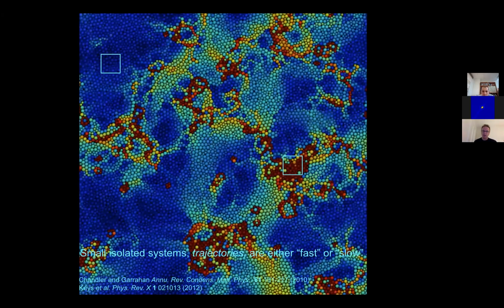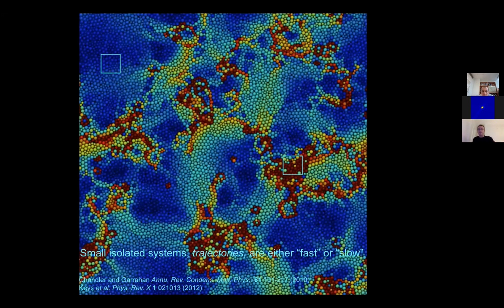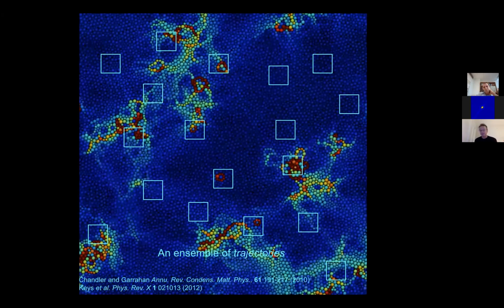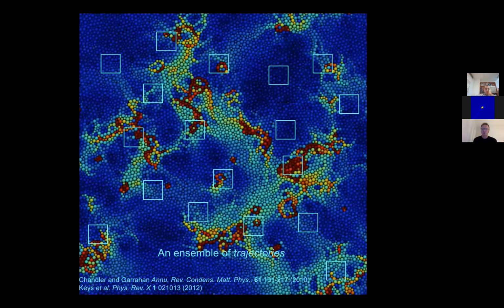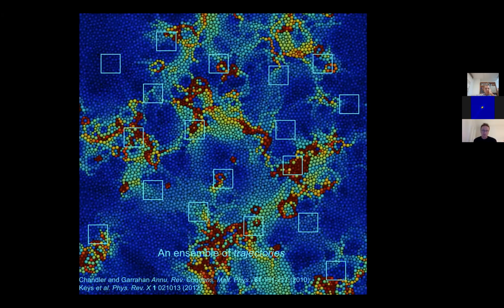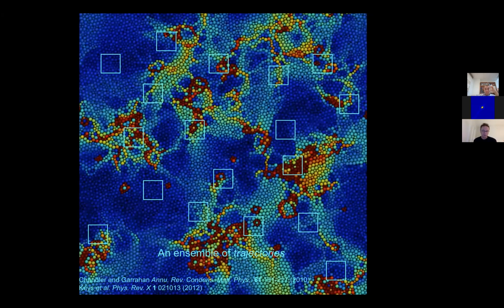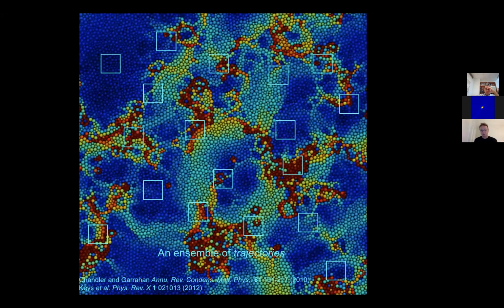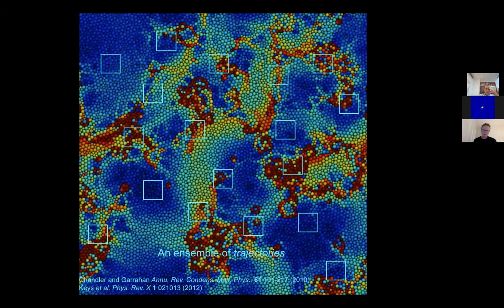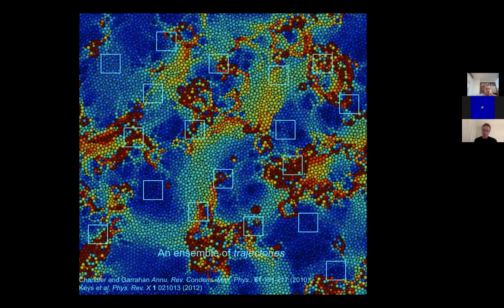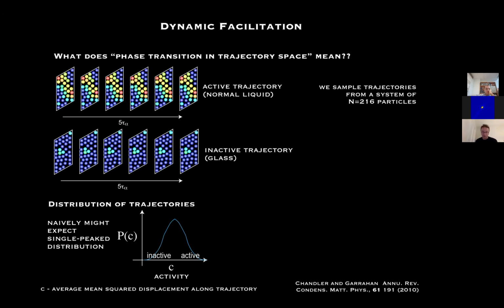And if we could take instead an ensemble of trajectories, we take many, many, many trajectories. So a trajectory is a small number of particles, a few hundred, run over some time, a relatively short time, and we consider in these trajectories, do the particles move, do they not move? Now, of course, we can do this and make this measurement, and what we might expect is that there would be a distribution of mobility or equivalently activity in these trajectories. So the graph on the bottom right of the slide is showing the probability of how much trajectories move or don't move. And this is what we would expect. C is what we call the activity. It's a measure of how much the particles move.